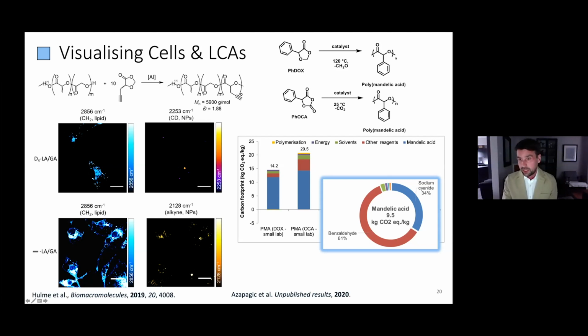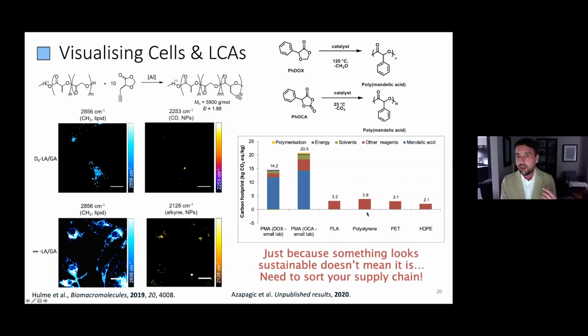And we can see that the bulk of this cost is the mandelic acid that we're having to contribute to the system. But what's really important here is that you really understand how that works in the system, because we're not really looking to try and replace the existing PMA synthesis. We're trying to look to change polystyrene. And I'm like, wow, we are actually really bad. Unless we solve the problem with the mandelic acid synthesis, we're actually contributing to the carbon problem, not trying to fix it at all. So just because something looks sustainable doesn't mean that it is. We're working with MIB now in Manchester to try and get much better routes to our mandelic acid that are more sustainable, which really will require us to couple those biological processes to renewable energy systems.